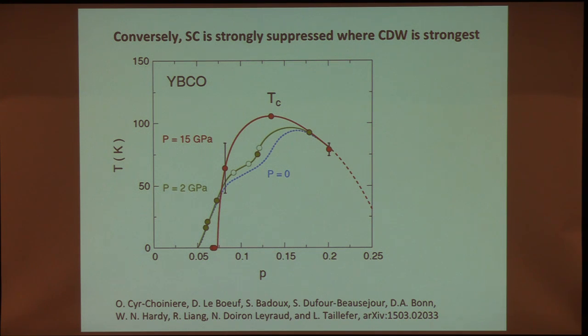We can do the other thing. I showed you that if I suppress superconductivity, I enhance the charge density wave. For reasons that I don't understand, it seems that even modest pressures at zero field tend to suppress the charge density wave. There's not actually direct evidence of this. This is inferred from transport, but it's probably correct. So here, this blue is the superconducting phase boundary at zero pressure. When enough pressure is applied to suppress the charge density wave, the superconducting TC is significantly enhanced. So these are in really delicate balance with each other. Just tip the balance one way or another, and one or the other order wins.